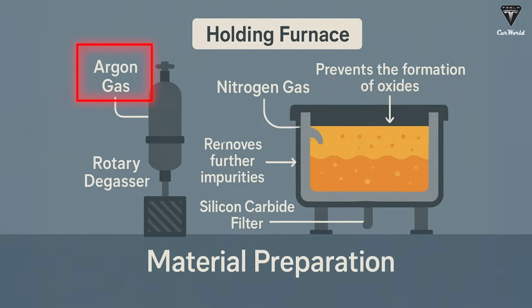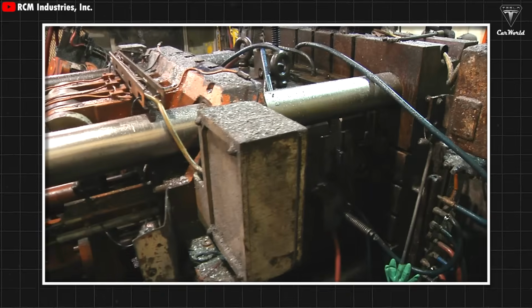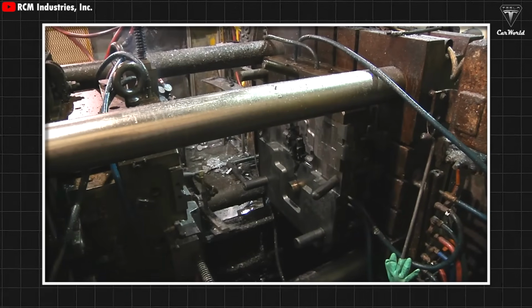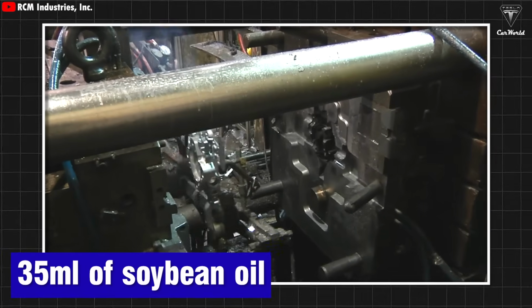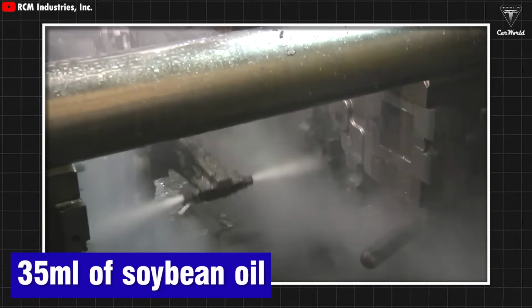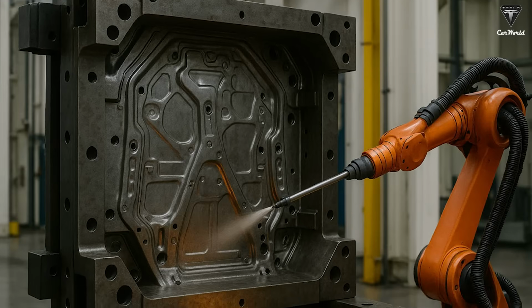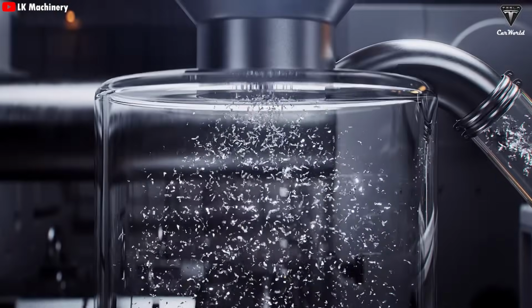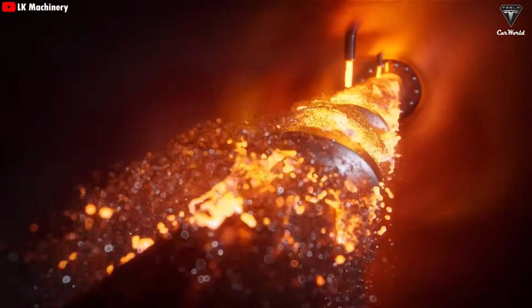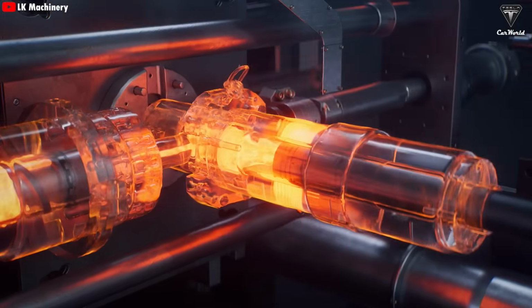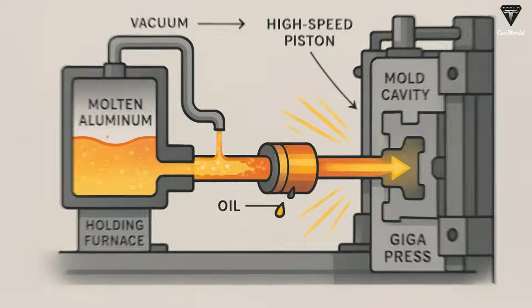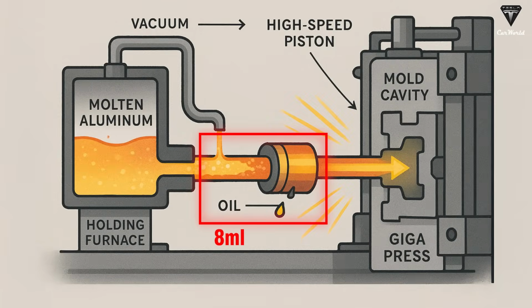Operators also use argon gas and a silicon carbide filter to remove impurities and particles larger than 25 microns. That's the material prep phase. Next up, mold preparation. Before each cycle, the Giga Press lubricates the mold surface. A robot sprays about 35 milliliters of soybean oil in a thin, even layer, kind of like applying non-stick spray to a baking pan, making it easier to release the cast part later on. Then, a vacuum system removes any air, and the molten aluminum is transferred from the holding furnace to the Giga Press's injection chamber. There, the liquid metal is injected into the mold cavity by a high-speed piston, which is also lubricated with about 8 milliliters of oil before each shot.